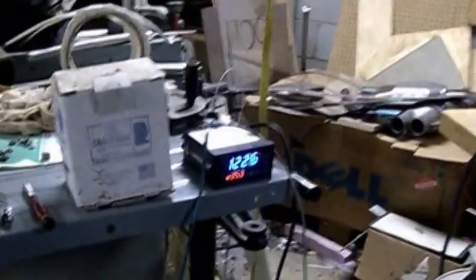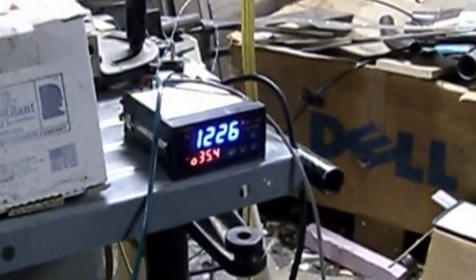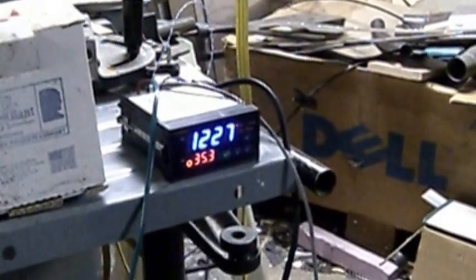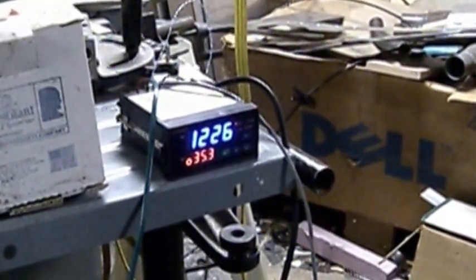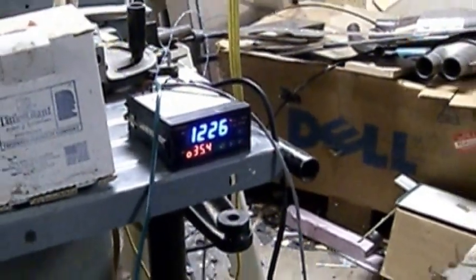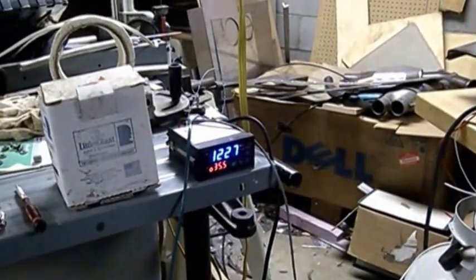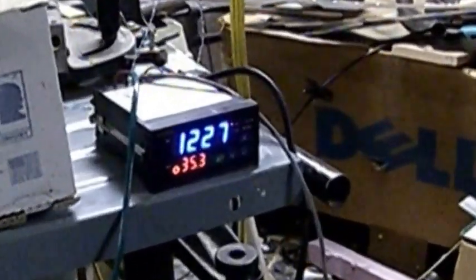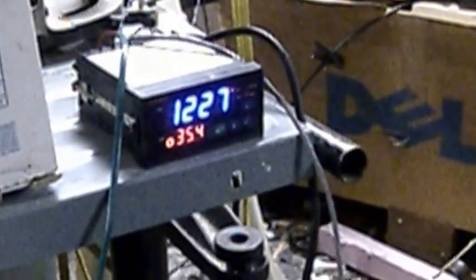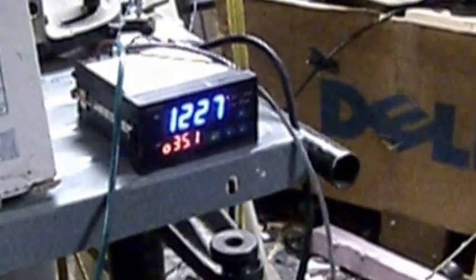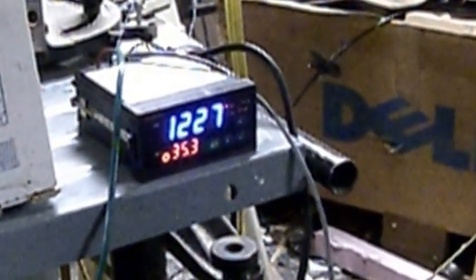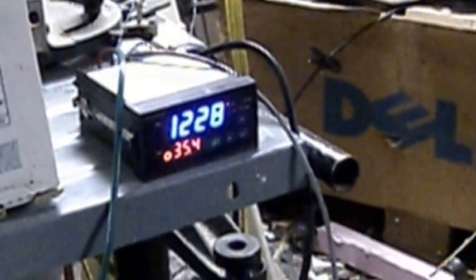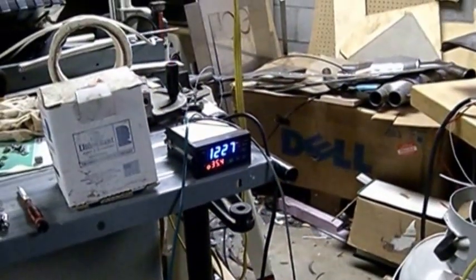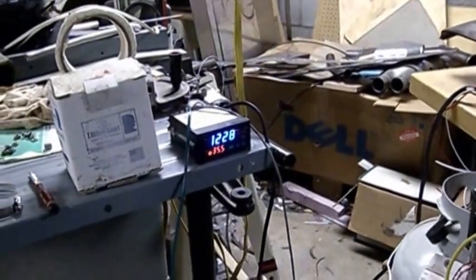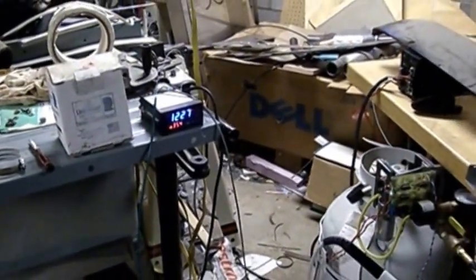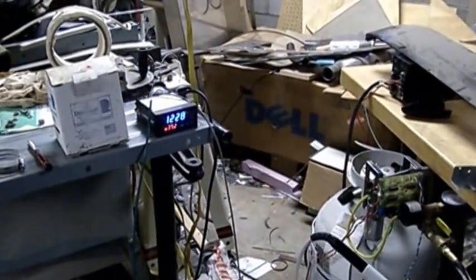You can see it here at 1226. So we're easing. We have about 100 more degrees to go before we hit the hold temperature. Last night I did a bisque firing, and as you can see, 35.3 is the gas valve setting. That was approximately the setting that the gas valve was at for the bisque firing at 1050. But with the preheat, you can see that I'm at 1227 and using almost the same fuel for a couple hundred more degrees. So that's working out really well.